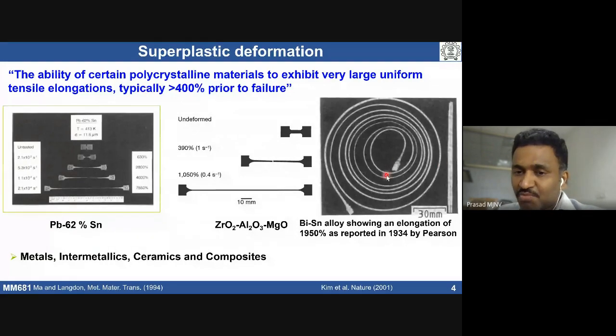This phenomenon was first observed and scientifically reported in the year 1934, given by Pearson. He had taken a specimen like this, made of bismuth and tin alloy. When it was deformed under tension at elevated temperature, it exhibited very large elongation to failure. The specimen still has not failed. In order to take a photograph, he spiraled the specimen after deformation. With respect to the original gauge length, he determined the percentage of elongation the specimen experienced, about 1950%. This was the first scientific report on the superplasticity phenomenon.